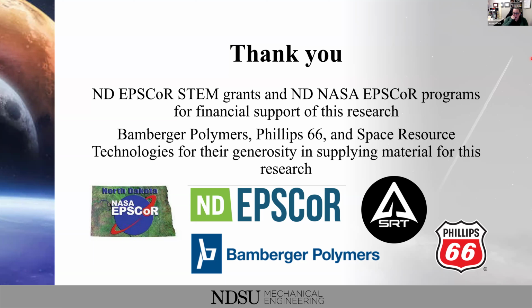Yeah, that's a really good question. We did not test layer to layer adhesion for our specimens. It is something we would like to do moving forward. We thought that would be more of an issue than it was in our testing. We thought a lot of our mechanical properties would be because the layer adhesion isn't the greatest, especially with our polypropylene. But then looking at them under a microscope, it was not as big of an issue as we thought it was going to be. And so we kind of put that on the back burner for the moment.